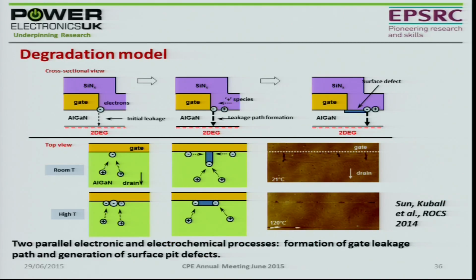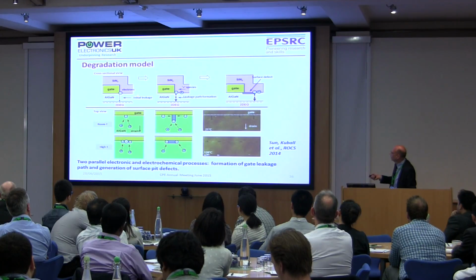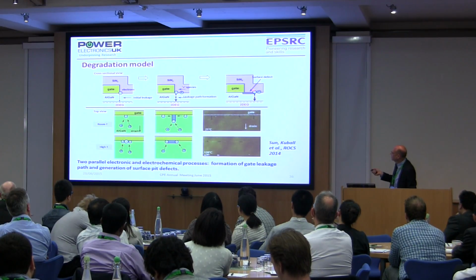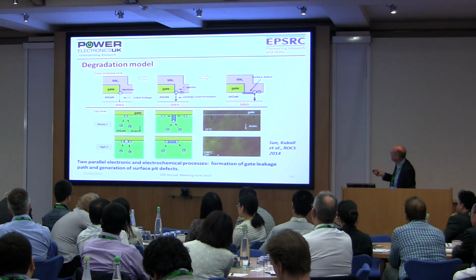And various mechanisms for that have been identified, and these have been published in the literature. They tend to occur right here at the corner of the gate. So there's the edge of the gate there. You can see these things grow, and they tend to grow out in fingers away from the gate, and eventually the leakage and the light occurs at the end of these fingers as they grow with time, and that's been published recently.